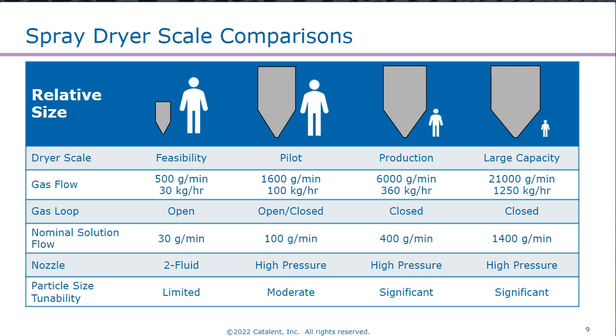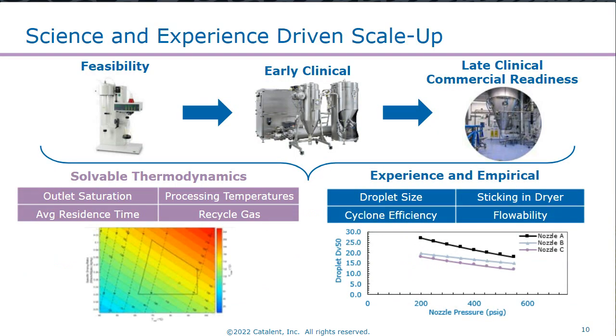I think it's important to note that spray drying processes done at that feasibility scale are producing powders that are highly representative of what you're producing at those larger scales. Physical chemical properties of those powders are going to match. Things like your Tg, which is important for the development of oral dispersion products, are going to match if your formulation matches. Dryer scales from that feasibility all the way to the large capacity cover about 2.5 orders of magnitude, which is a huge change in process capacity, which leads us to needing to use really good techniques for that scale up.